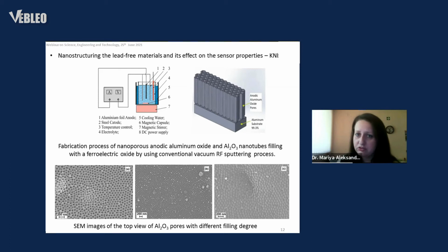One of the approaches that we used, we applied for the potassium niobate. It was anodization of aluminium oxides. So aluminium is subjected to a chemical process of anodization, and during this dissolving of aluminium, it is oxidized, forming a specific kind of array of nanopores. And if the thickness of the aluminium is high, these nanopores become nanotubes. They could give a good template to fill these nanotubes with our functional ferroelectric coatings, then to dissolve the nanotubes and to leave attached to the surface only nanowires. But they are very regularly single-axis organized because they strictly follow the template of this aluminium oxide.